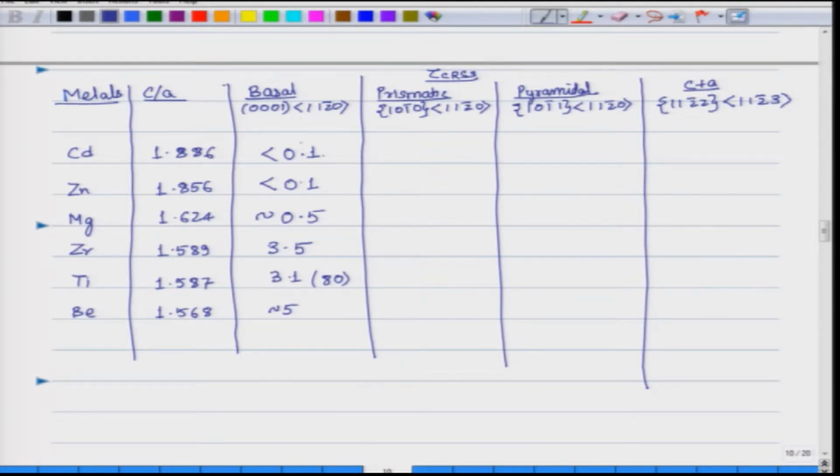So, clearly you can see that as the planar spacing of the basal planes is decreasing, the tau CRSS values are increasing, meaning it is no more as easy a slip system or as easy a glide plane.